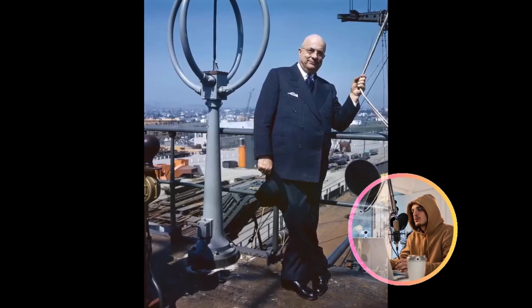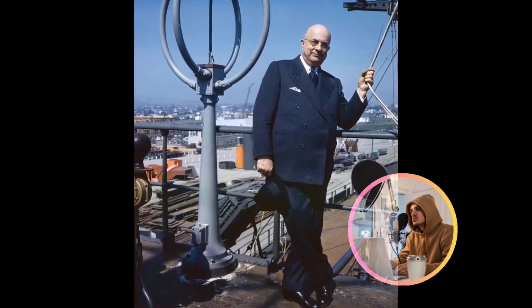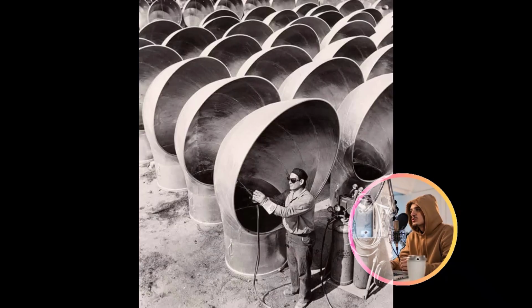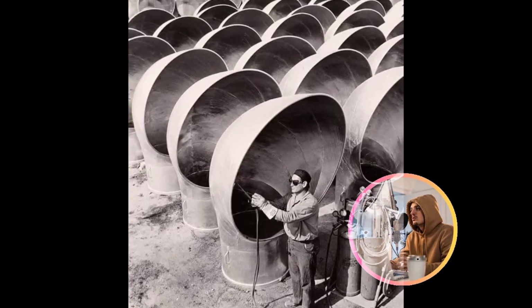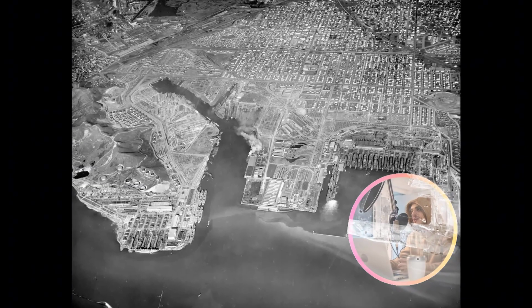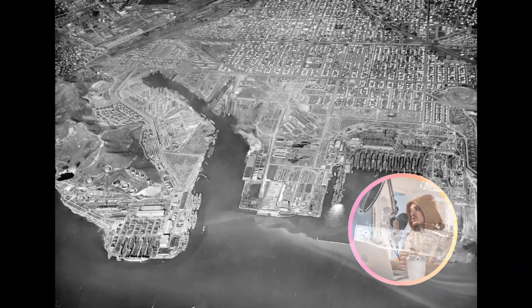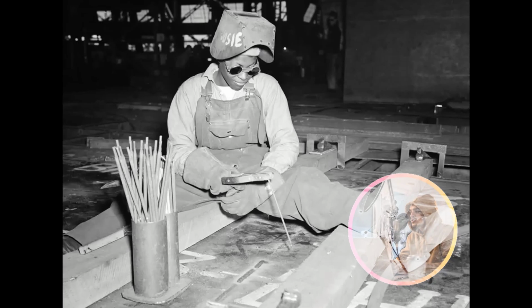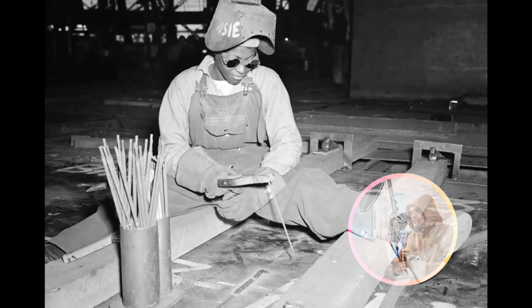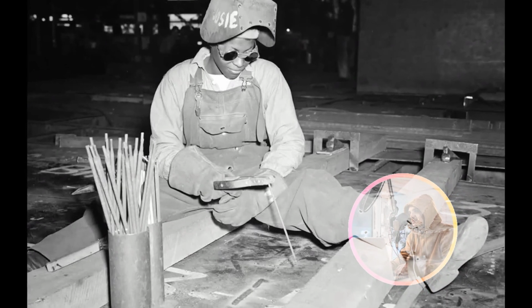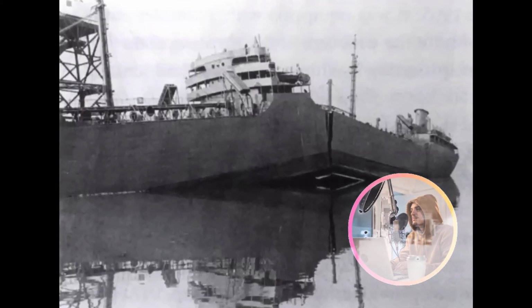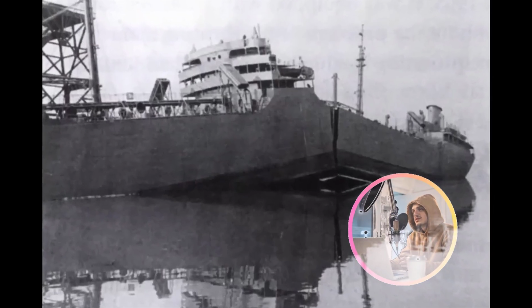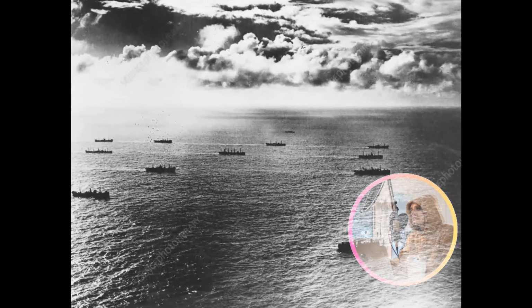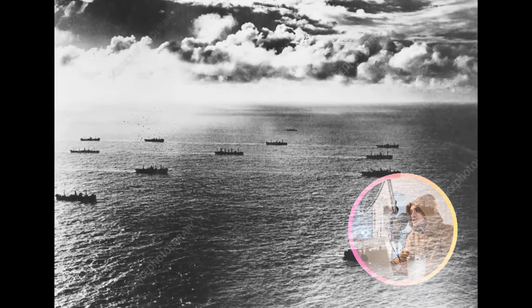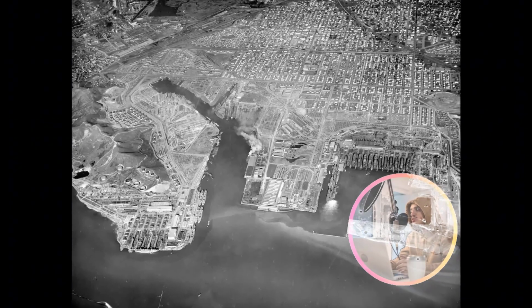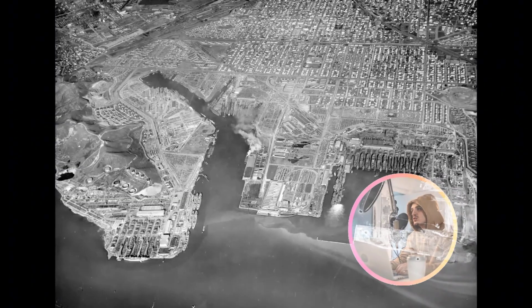The skeptics found ample justification for their doubts when the keel of the very first Victory ship was laid in February 1944. Its initial construction consumed 18 days, a pace notably slower than the existing records for Liberty ship production. Kaiser shipyards, it seemed, were no longer conjuring miracles. They were merely building vessels at what was, by comparison, an impressive but not astonishing speed. The second Victory ship, though marginally faster, still required 16 days to complete. Critics were quick to declare the entire program an unequivocal failure, citing it as irrefutable proof that achieving both quality and speed in wartime shipbuilding was fundamentally incompatible.